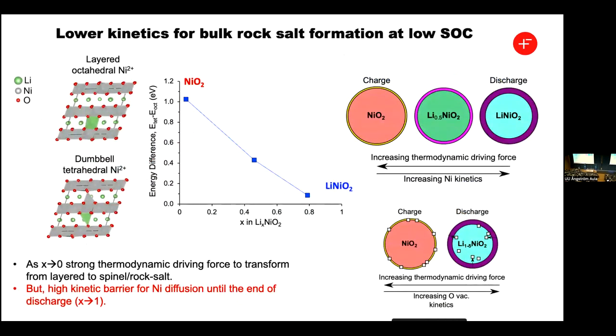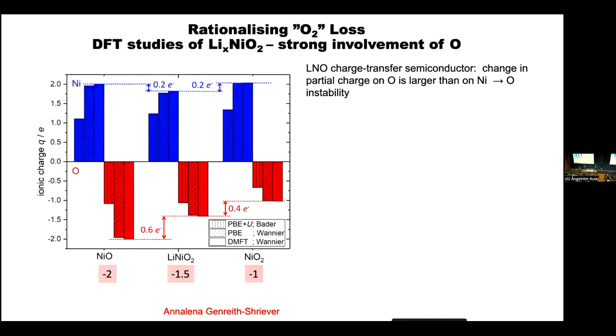So you can see it's easy to form a tetrahedral nickel at high voltages, but it's very difficult to move those nickels. And so the mechanism that we have, at least that partially explains this, is that at high voltages, you pull out the lithiums, the nickels drop into the tetrahedral sites, but you've got to go down to low voltage to actually grow the rock salt phase. And that's why this sort of cycling backwards and forwards is critical. And I just want to quickly talk about why this happens.